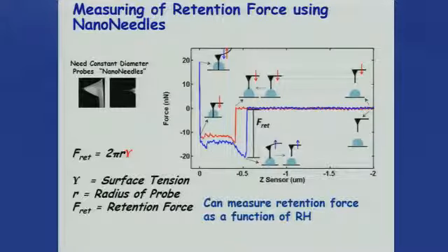The only thing is that you need to have very specific what we call nanoneedles that have a cylindrical shape. They are 50 nanometers in diameter. And the idea is that you then come into contact with the particles. So as you can imagine, you need to have a corresponding ratio between the size of the tip relative to the size of the particle. So you're talking probably half a micron, maybe several hundred nanometers. So this is our limitation at the moment.